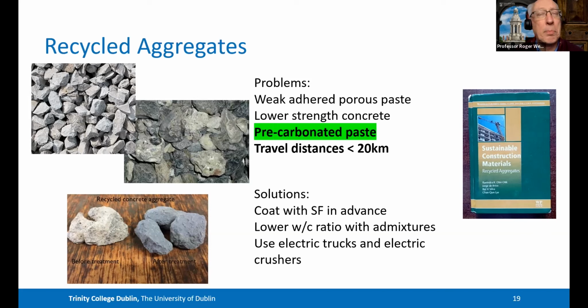But when you crush the aggregate up and you leave it out in the open, then that aggregate actually absorbs a lot of carbon dioxide. So the adhered mortar actually is precarbonated, and that will absorb some carbon dioxide, which is obviously good news from a sequestration viewpoint. I think we can get over the high water content problem and the lower strength by perhaps coating the aggregates. You can see that bottom left-hand corner, by coating the aggregates with a silica fume paste or slurry, and that closes up the pores, and then we can proceed as normal.